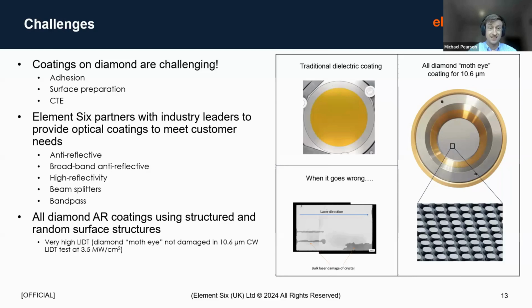So one is adhesion of the coating to diamond. The diamond surface is typically pretty chemically inert. If we were to try and braze a piece of diamond to another material, we'd typically put a metallization on that consisted of a carbide forming element, so titanium or chromium, for example, which forms a very strong bond with the diamond. When we're talking about optical coatings, we often can't do that. We're quite limited in the materials that we can use because we need the optical performance. So adhesion can suffer as a consequence.